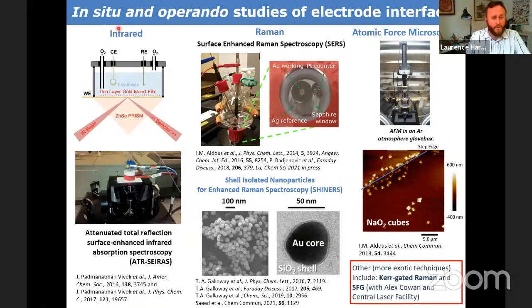The systems we're interested in with this technique are really looking at changes of surface speciation at the actual electrode interface. We use nanostructured gold electrodes, which have been evaporated onto a prism, which is optically transparent to the infrared. So we can enhance the local signal and see surface adsorbates within this type of electrochemical cell. We've used this pretty much exclusively looking at lithium-oxygen or metal-oxygen environments to understand reaction mechanisms of alkali metal ions and oxygen that occur at the interface.